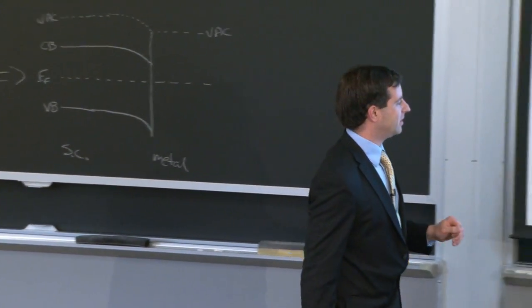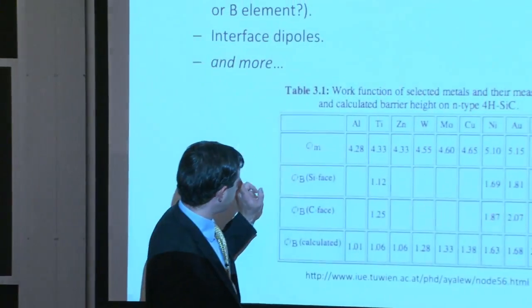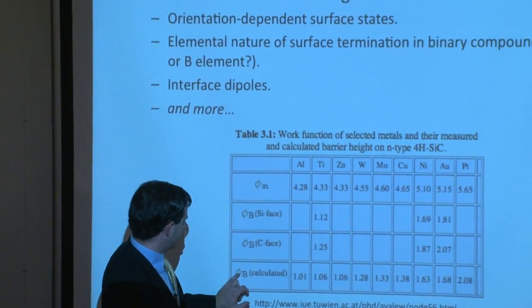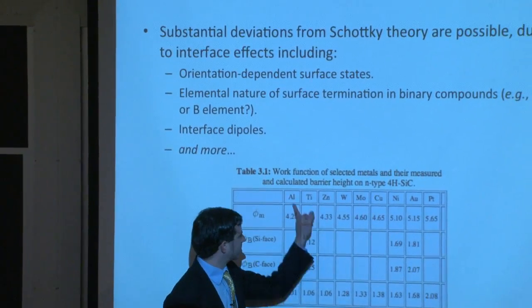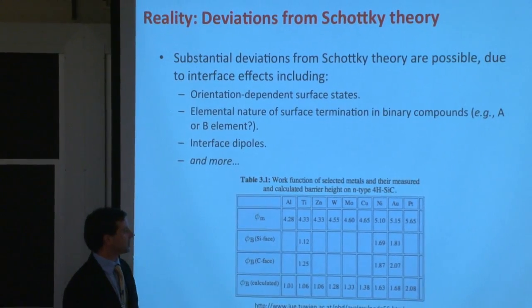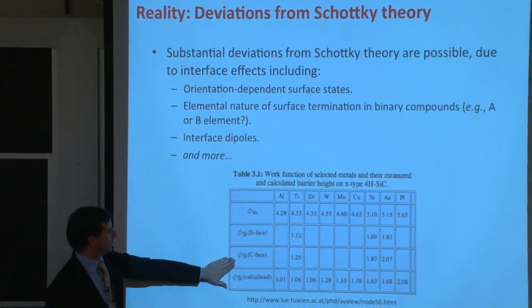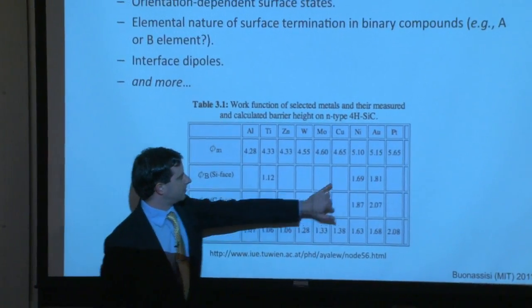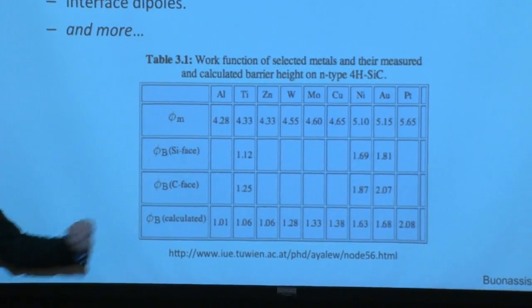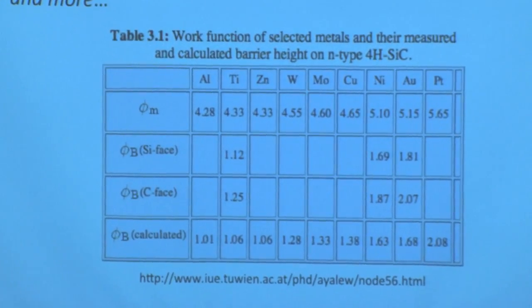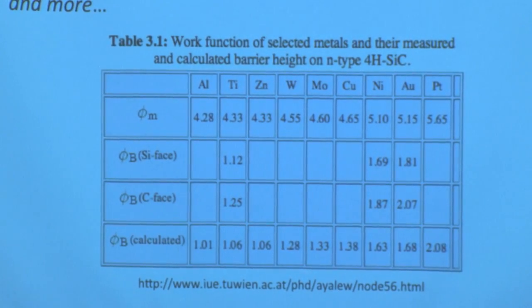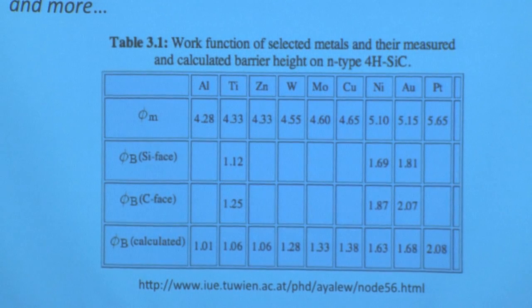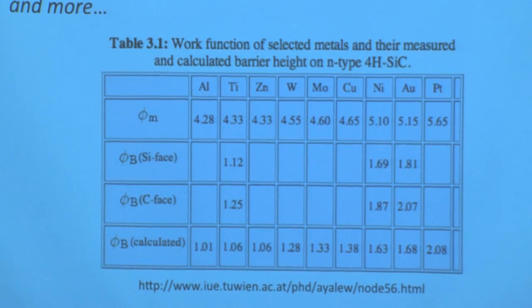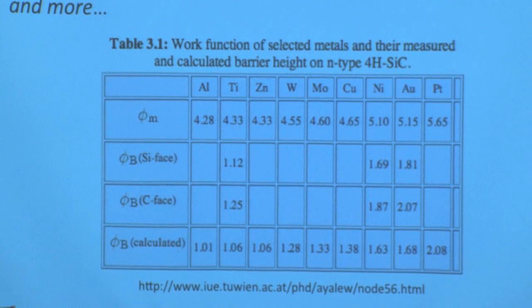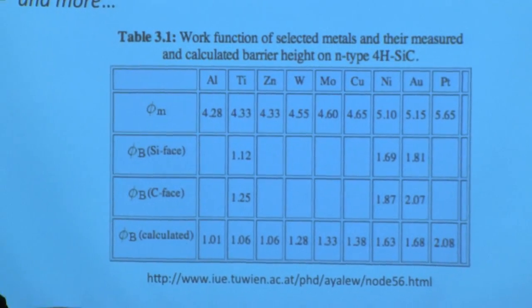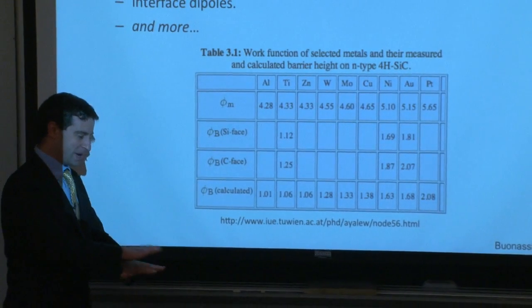This is an example right here of the calculated, make sure I get all my variables right. Yes, so work function of the metal, the calculated barrier height for different metal species on a certain polymorph of silicon carbide. And these are the measured barrier heights for different metals, titanium, nickel, and gold, at different faces of the silicon carbide. So if you have a binary semiconductor, meaning a semiconductor comprised of two elements, if you terminate at a surface and you cut the plane just right, you could wind up exposing a row or a plane of silicon atoms or of carbon atoms, if you have silicon carbide, depending on where you cut.